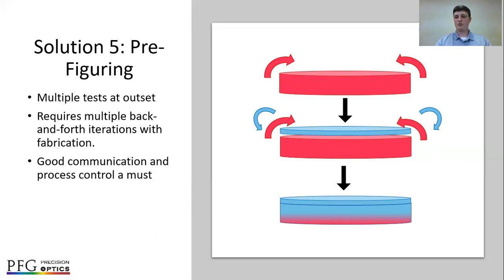Now, this requires multiple test runs up front. It requires multiple back and forth iterations with fabrication and coating, and requires very good communication and coordination between fabrication and coating, and requires high process control. PFG finds this to be an advantage for us because we have both fabrication and coating under the same roof, and so we can expedite that coordination and make it as seamless as possible.